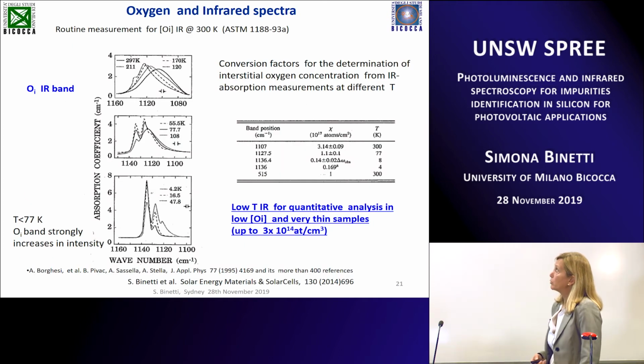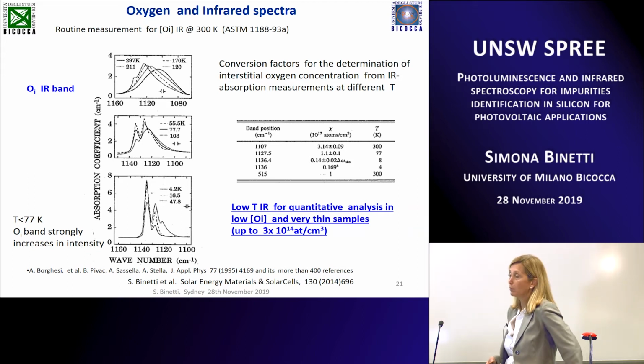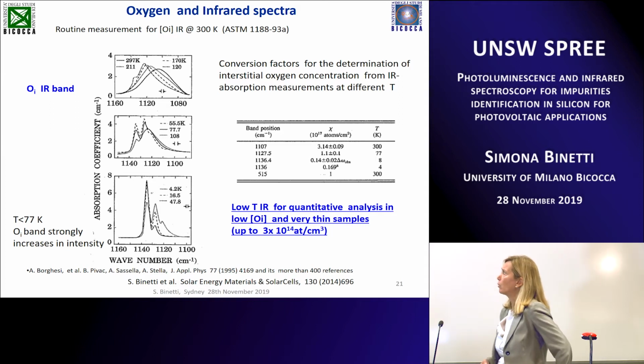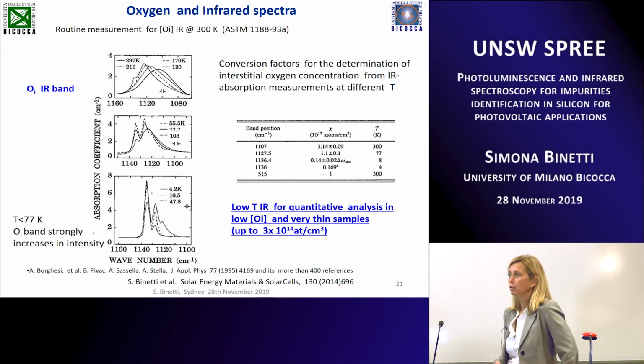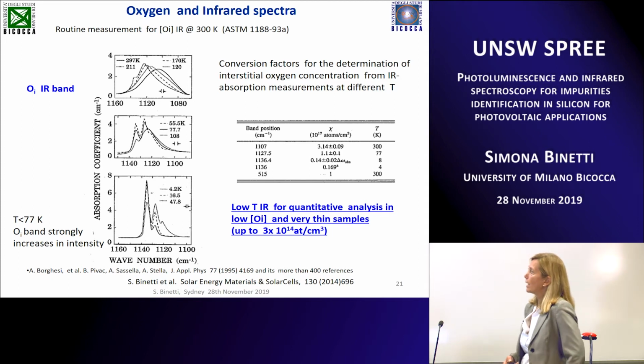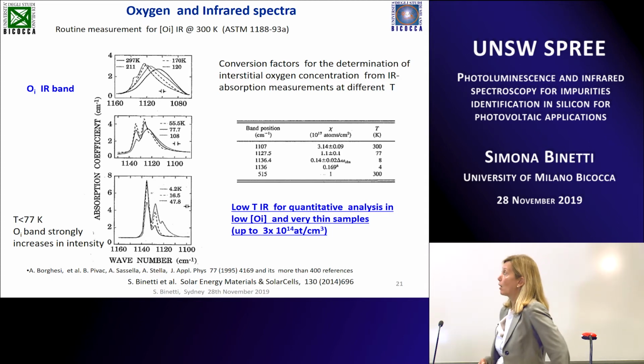So let's move to oxygen. Oxygen is a very well-known impurity. The routine measurement is with infrared spectroscopy at room temperature, by detecting a band at 1,107 centimeters -1. But if you have a low concentration of carbon, you can perform measurements at lower temperature, just liquid nitrogen or lower, and in this case the infrared technique is much more sensitive to low interstitial oxygen, and it's also useful in the case of very thin samples.